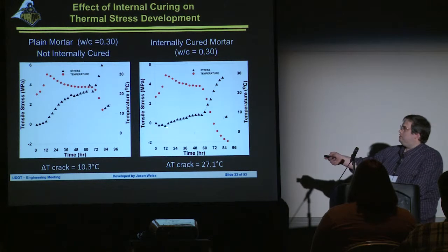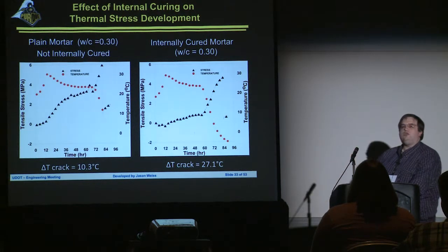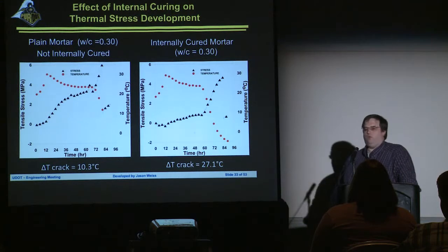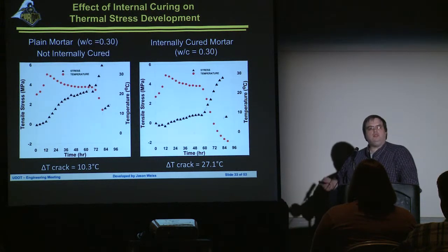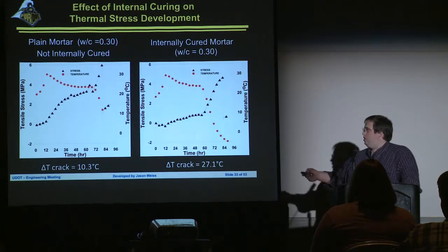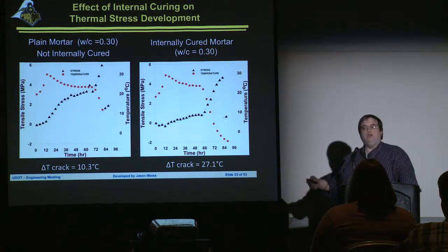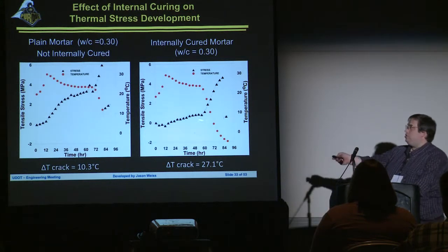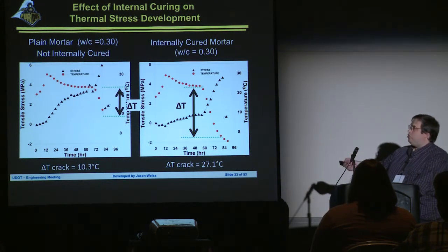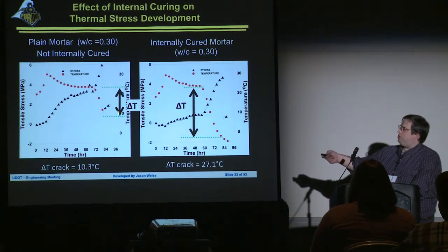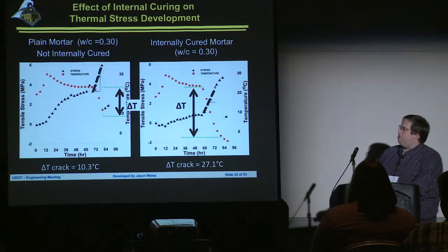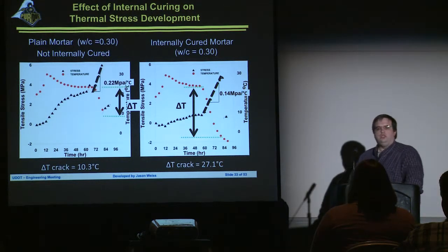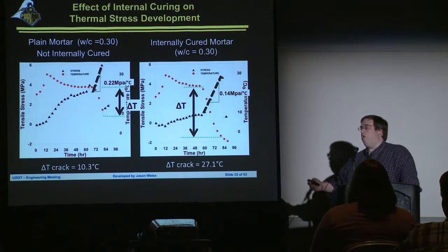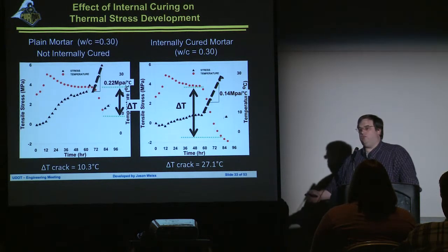Your internally cured mix, we do the exact same thing. It takes a 30-degree temperature swing, actually 27.1, to cause cracking. So we've built in a lot more robustness into this system. We can undergo a much more substantial temperature swing before the system would crack. This helps us to get that concrete through this sensitive time, that first week, that second week after casting, to make sure we're going to have a concrete that remains uncracked. So what we can see is we get a little bit of a benefit here where we start to change it from a 10-degree swing to a 27-degree swing. We also notice, though, that there's a much slower stress development in the system. And this is due, one, to the fact that there's more moisture in the system, and that changes the coefficient of thermal expansion.